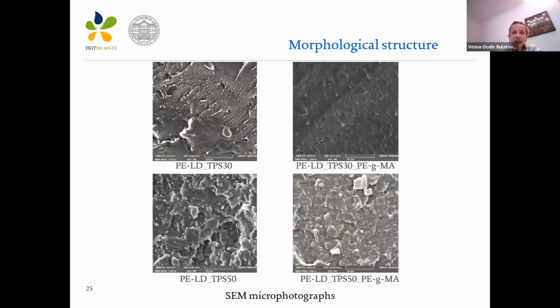In this slide, we can see the same micrographs of polymer blends with low and high content, without and with the addition of compatibilizer. Without compatibilizer, we can see that PELD and TPS phases were incompatible. They create a two-phase morphology in which the particle domains of TPS are dispersed in the PELD matrix. Cavities are evident as a consequence of pulled out TPS particles, which indicates weak interfacial adhesion due to the hydrophilic character of TPS and the hydrophobic character of PE-LD.